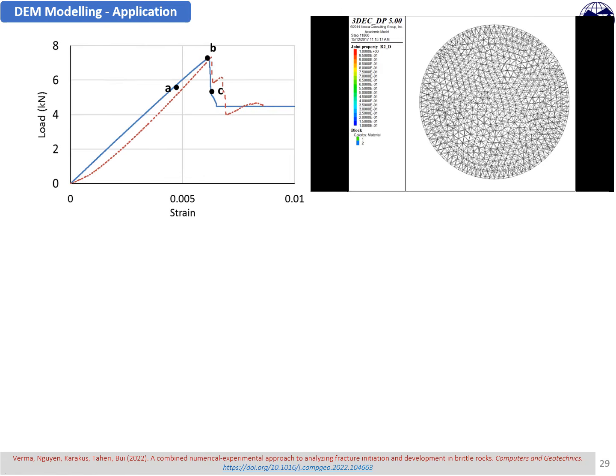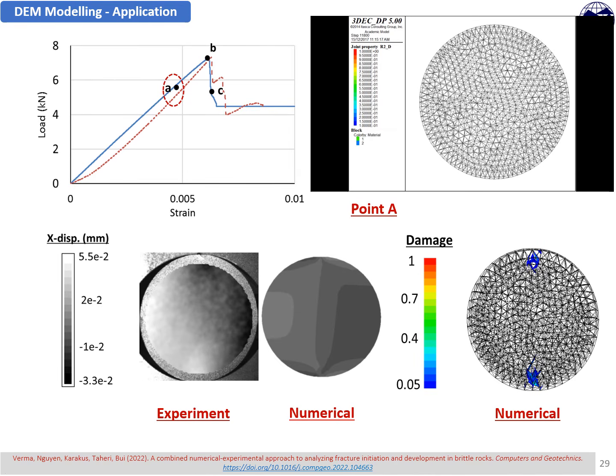The next set of experiment and simulation in this process of calibration was the Brazilian disc test. We can see that the load versus displacement response or strain response from these two sources, that is, one from the numerical model and the other from experimentation, are pretty much well aligned. And at stage 1 we can see that the local scale damage started from the loading end, and that corresponds well in both numerical and experimental results.